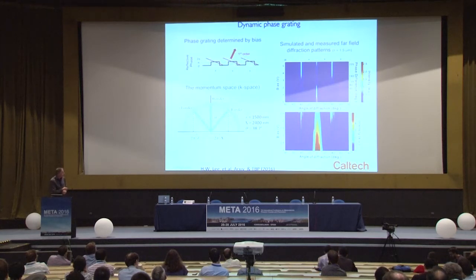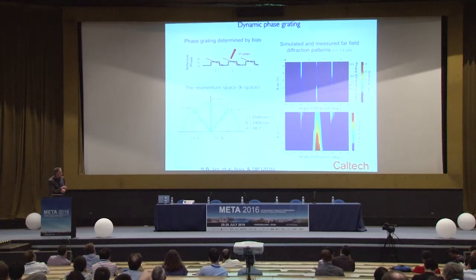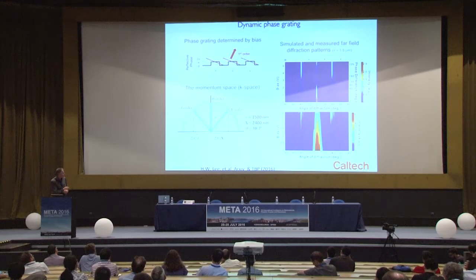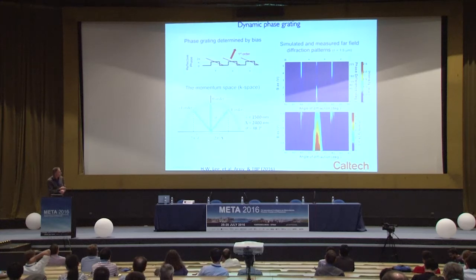And indeed, if we now bus the antennas together in groups of 3, then groups of 3 antennas actually act as a tunable phase object that's about wavelength in scale. And so if we now tune groups of 3 antennas in a periodic bias modulation with zero bias applied to the next group of 3, we can form essentially a switchable diffraction grating, where we expect the reflectance to go from a characteristic 0 order reflection to one that is dominated by plus and minus 1 order reflection. This is a simulated change in the phase and the scattering response as a function of angle